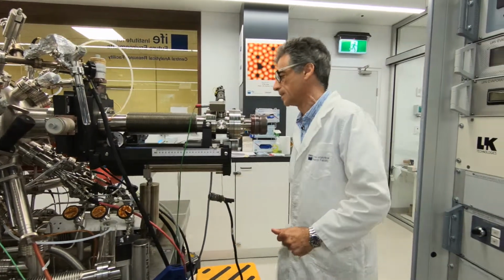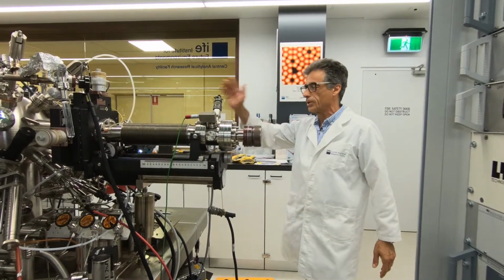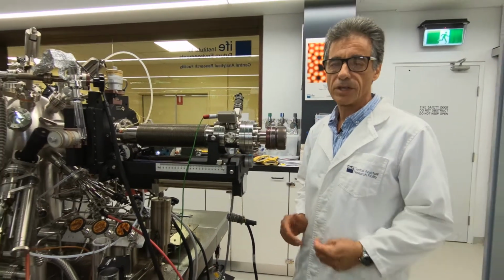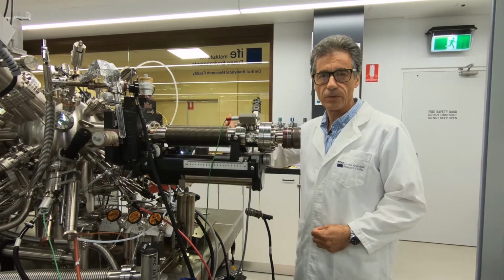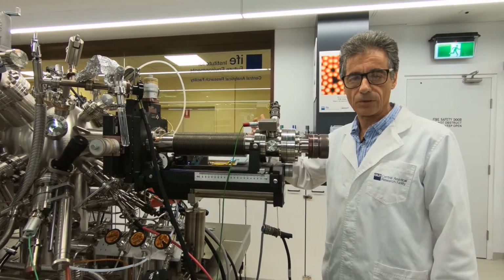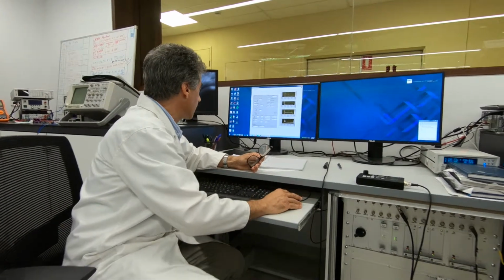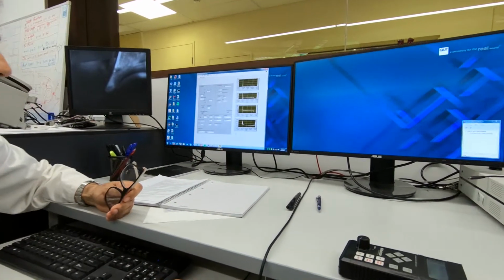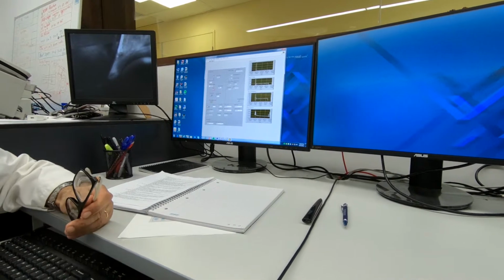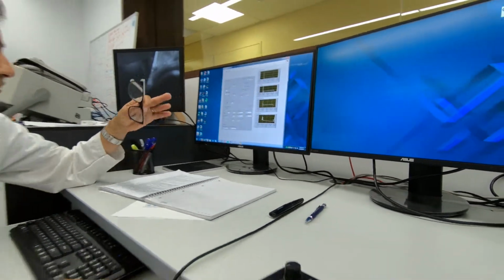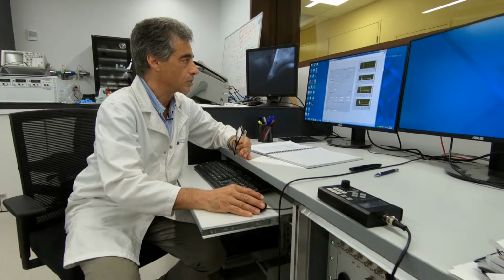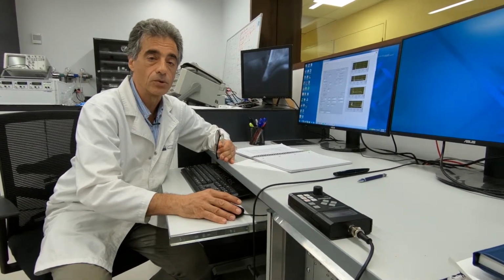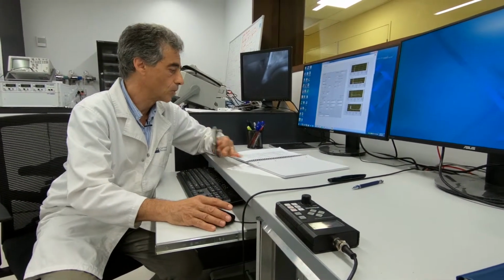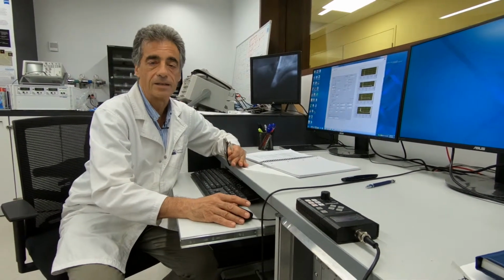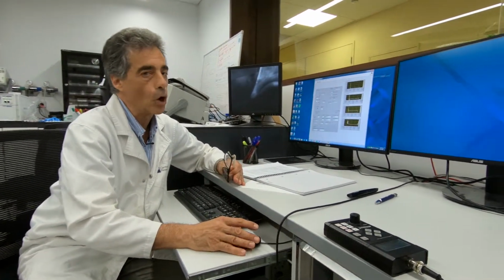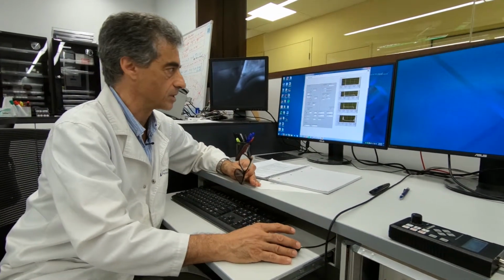Here we are. Okay, now we point the pyrometer to measure the temperature, and we go to the computer to control the current in order to heat the sample. This program here allows us to control the power supply, and we set up the desired current. We need a preheating step in which the silicon carbide goes to 600 degrees in order to clean the surface, eliminating all the contamination that is on the surface.